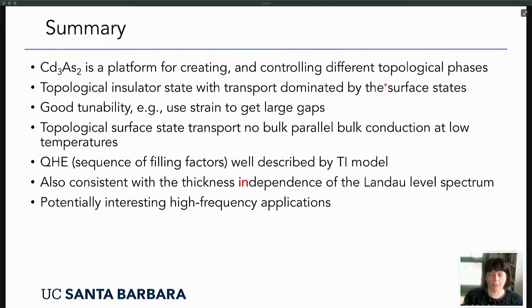And it's relatively easy to open a band gap by, for example, applying strain or confinement. It has very good tunability, so it responds nicely to a number of things. What I showed you is strain and confinement. We can, for example, use strain to get even larger gaps, and I showed you this further minimizes the transport through the bulk states, which is important for the transistors, but also if you want to apply them as topological insulators. And I showed you that we have a very nice description of our quantum Hall effect and the thickness independence of the Landau levels, which really confirms what we should expect for a 3D TI. So it's very nicely behaved in that we really have this 3D TI model to describe the transport we are seeing.